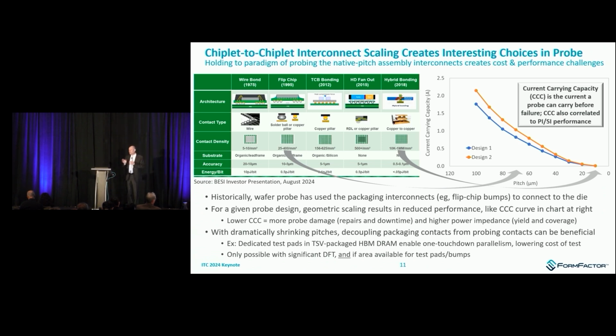You can see, we'll see the example with HBM in a second. But with those dramatically shrinking pitches, people, customers, manufacturers are resorting to some other techniques. Maybe dropping dummy pads in between the hybrid bonding contacts, using those as dedicated test contacts, and then relying on some degree of DFT. There are cases on customer roadmaps, however, where that's not possible. There's not enough spare area on the die to drop in a test contact that is easier to probe, simpler to probe than the packaging contact.